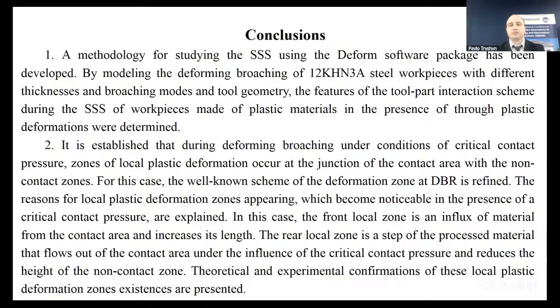It is established that during deformation broaching under the condition of critical contact pressure, a zone of local plastic deformation occurs at the junction of the contact area with the non-contact zone. For this case, the well-known scheme of the deformation zone at deforming broaching is refined. The reasons for the local plastic deformation zone appearing, which becomes noticeable in the presence of the critical contact pressure, are